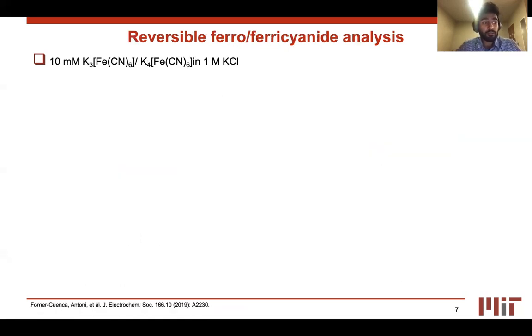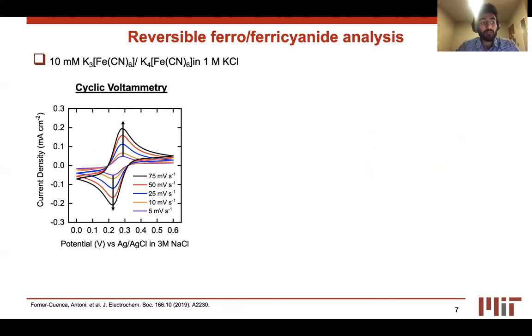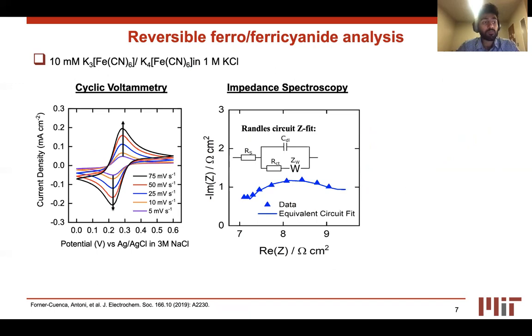In the reversible regime, 10 millimolar ferro ferricyanide in 1 molar KCl was analyzed. Firstly, the CV plot indicates reversible behavior as shown, where the peak-to-peak separation was around 57 millivolts as expected. In addition, electrochemical impedance spectroscopy was also carried out, which was used to determine the charge transfer resistance of the system. Here, a Randles circuit was used to obtain an equivalent circuit fit to the experimental data from which the charge transfer resistance was extracted.